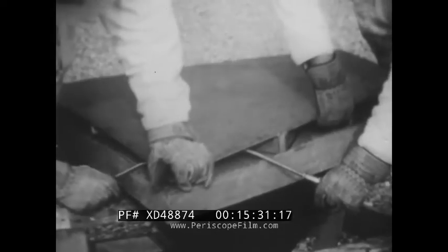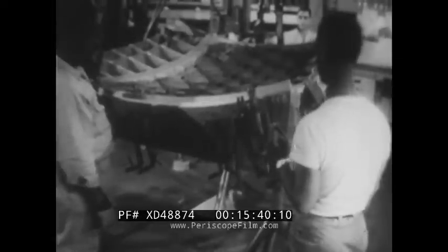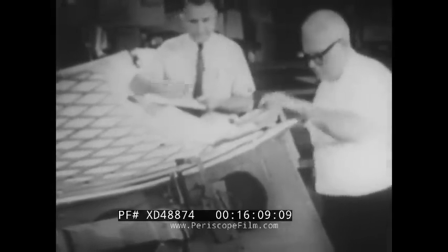This forming procedure is repeated 3 times, and the gore is annealed after the first 2 explosions. After the final forming operation, the gores are returned to the Los Angeles division, where they are clamped in precision contour fixtures and heat aged to control and maintain dimensional stability. Finally, the skin thickness between the weld lands is reduced by chemical milling to eliminate weight. Throughout the entire procedure, progressive inspections ensure accuracy of trim lines, hole locations, and the maintenance of contours.